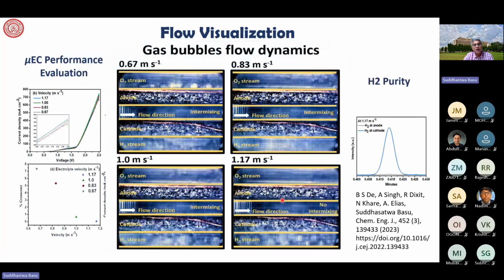So that is what I want to show you here; this was the side view, and that was the front view that I was showing. You can see at 2.5 volt, I can get about 750 milliampere per centimeter square, which is a good amount of current for such a small cell. And the previous design, which Hashmi et al. from EPFL have shown, got about 70-80 milliampere per centimeter square, and it has improved by 10 times because of our design and because of the catalyst that we're using.